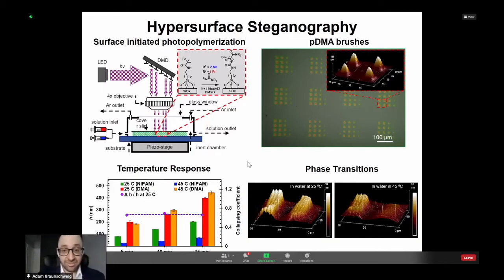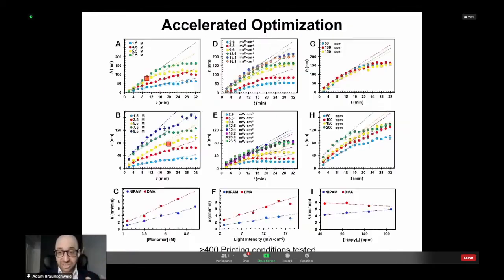So here in the bottom right, what you see are the 2 polymer blocks of identical heights. You have the non-responsive polydimethylacrylamide on the left and the responsive polyNIPAM on the right. And upon heating, you see only the NIPAM collapses. And one thing that he discovered was regardless of polymer height, the collapsing ratio stays constant. But the real challenge here is Jurjan had to find conditions under which he could grow brushes of exactly the same height. So to do that, he tried over 400 different polymerization conditions illustrated in these graphs,